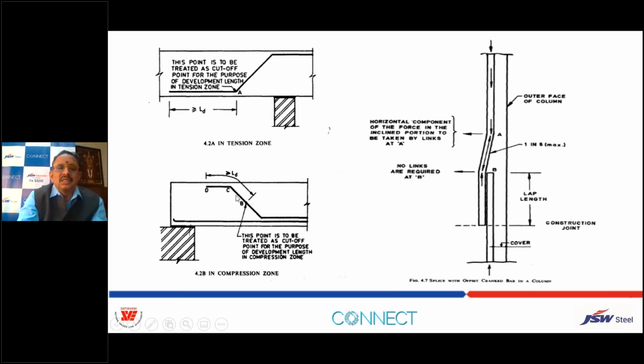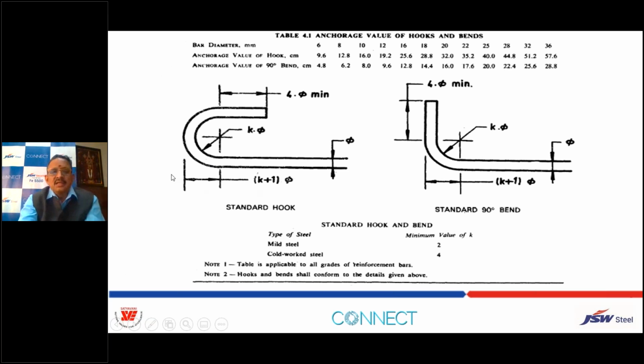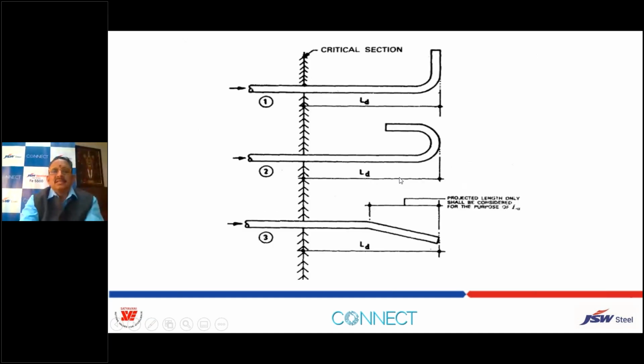So we all know about these development lengths, anchorage zones, and lap splice and transition zones. So we have to keep all of this in mind. For MS bars, we used to have the standard hook, and with the HYSD and HSD bars and TMT, we have this end anchorage, hook and bend. And then these are all the different hooks and bends that are required to be done. This is very important for maintaining the development length along with the anchorage. In fact, in some of the provisions, we have come across that you should not depend more than 50% on the bond. 50% you depend on the anchorage only. So it's very good to eliminate the slippages, particularly in fatigue zones actually.